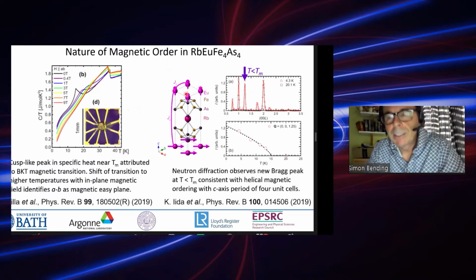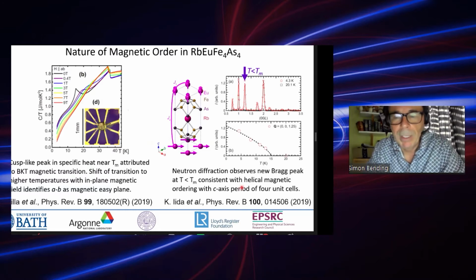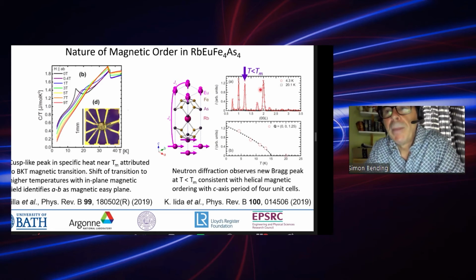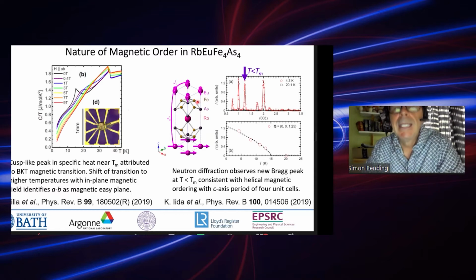The actual magnetic structure, so we see here each europium has a large spin moment of several Bohr magnetons. The magnetic structure was elucidated by Iida et al. using neutron diffraction. And what they saw in their diffraction measurements, as they dropped below the magnetic ordering temperature, they saw a new peak here, which was consistent with helical antiferromagnetic ordering, where the spins are lying within the AB planes, but they are rotating with a period of 4 unit cells.